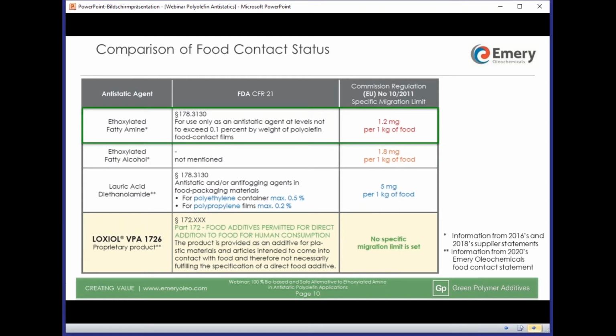For ethoxylated fatty amine, you see according to FDA, you are not allowed to use more than 0.1% of it in a polyolefin film made for food contact, no matter if the antistatic effect at this dosage is sufficient or not. For EU 10/2011, there is an SML, specific migration limit, of 1.2 milligram per kilogram of food.